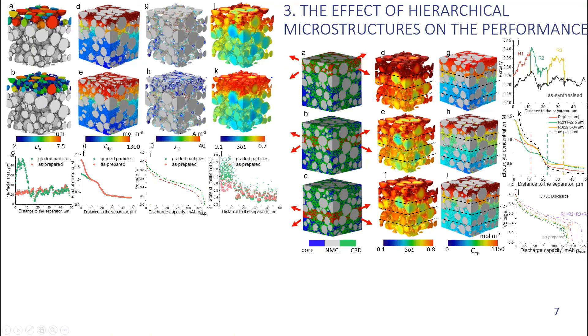Here, we expand the pore size by 250 nanometers at three locations away from the separator and check how it affects the rate capability. As the results show, the first case has the highest rate capability and no major difference between the other two cases. This indicates that the rate capability of the electrode is primarily determined by the pore morphology in the vicinity of the separator rather than other locations. Even though in the other two cases the electrolyte concentration is higher at the bottom half of the electrode, the rate capability is still inferior to the first case.